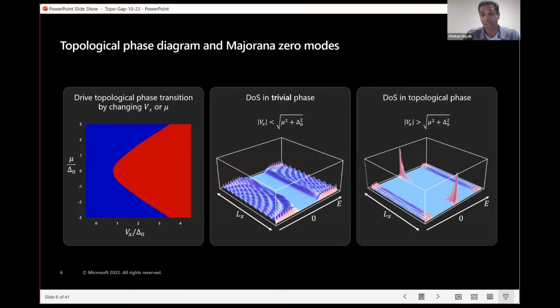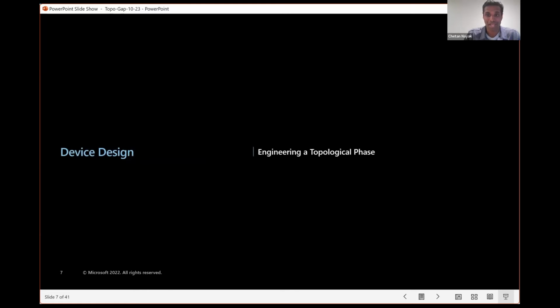And then in the high field phase, it's actually almost the same density of states. This is the local density of states, so this is energy here versus position along the wire here. And there's a gap in the bulk of the wire, but at the ends you have these Majorana zero modes. The signatures in the density of states are these peaks in the local density of states at the ends of the wire. Okay. Now, again, that's a very highly simplified and idealized model.